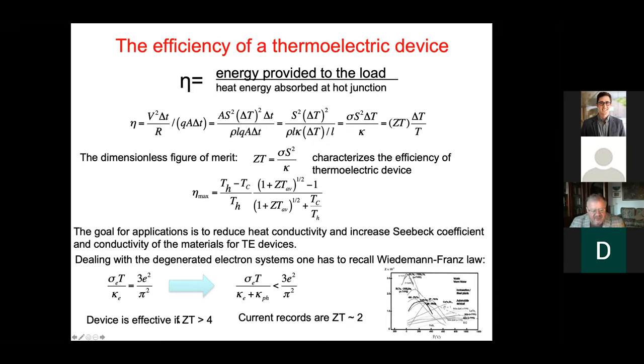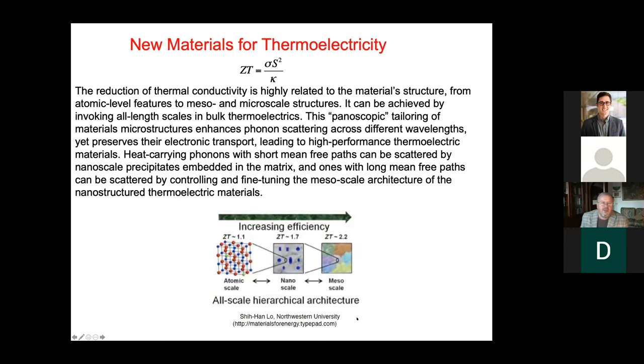So the device would be effective if ZT will be larger than 4. Current records are around 2. So in the 90s, the new materials based on these ideas and nanotechnologies, the new materials for thermoelectricity appeared. So the main task was to increase the figure of merit. The reduction of thermal conductivity is highly related to the material structure, from atomic level features to meso and micro scale structures. It can be achieved by invoking all length scales in bulk thermoelectrics.